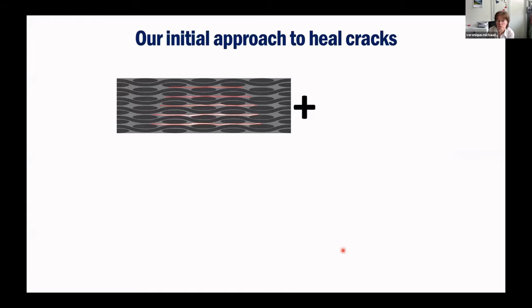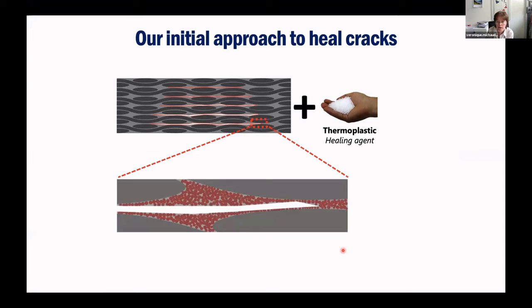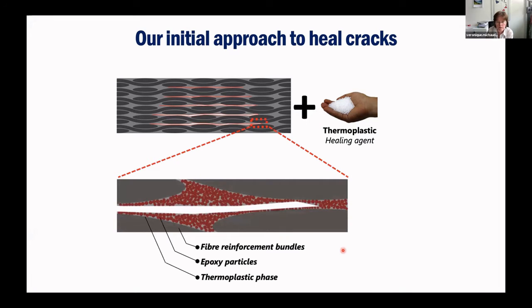So our initial approach was to say, okay, we can use a traditional composite, but instead of having only an epoxy matrix, we use a thermoplastic healing agent inside the matrix. And the idea is that you have a crack, you have these fiber reinforcement bundles here, schematized, of course. And then in the resin-rich region, you have this mixture of epoxy and thermoplastic phase. So if you have a crack, by moderate heating, for example at 150 degrees, then the thermoplastic phase should melt and fill the crack and help to solve this issue. Of course, there are many things that remain. The epoxy remains where it is, so the crack is mostly filled with a thermoplastic phase and so on, but this is the idea.